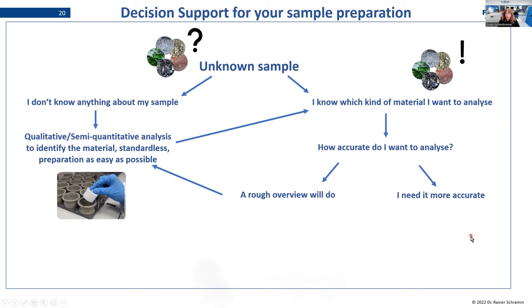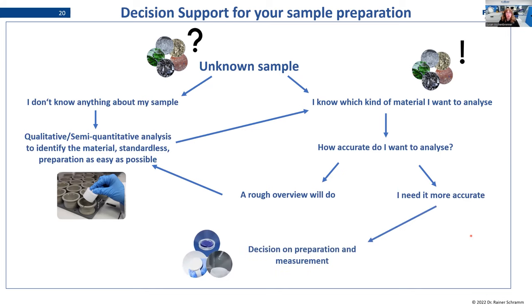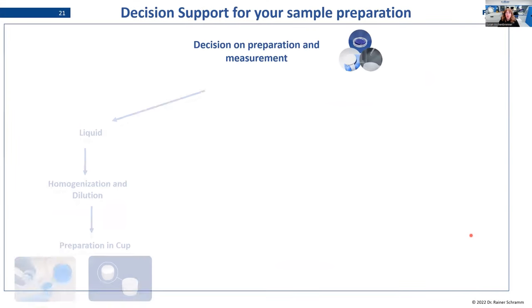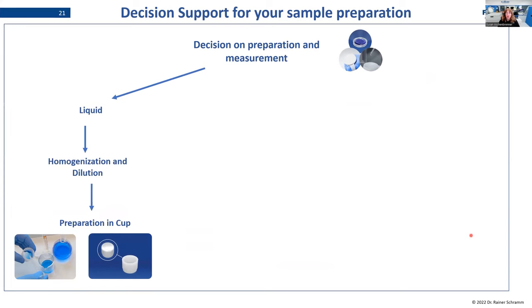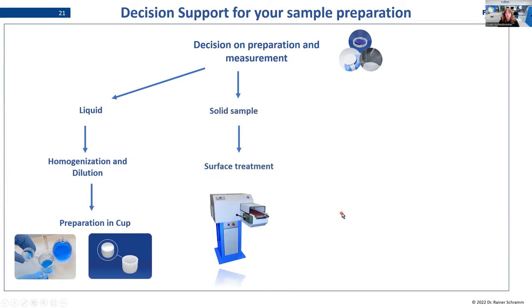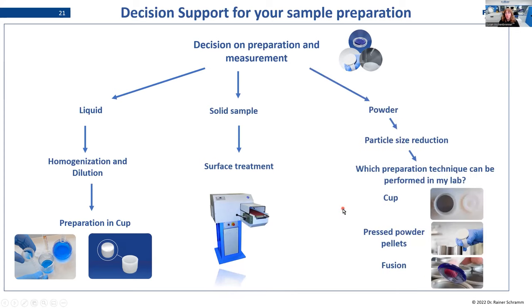Most of the time I will need it more accurate, and then I have to do the decision on preparation and measurement. And this decision depends on which kind of material I have. If I have a liquid, I have to think about preparation in terms of homogenization and dilution. For special liquids, there might be a special preparation necessary, but then I can prepare just in a cup and I'm good to go and measure. For solid samples, I need to think about surface treatment. And for powders, I need to think about particle size reduction, maybe, maybe not. And then I have to consider, do I want to prepare in a cup, as a pressed powder pellet, or in a fusion process?